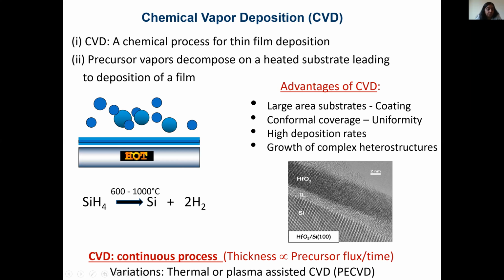Sometimes you do thermal CVD, so you go to high temperatures. In case you want to grow films at lower temperatures, then you can introduce another parameter, that's plasma, that can bring down the temperature of deposition drastically. So it's called plasma enhanced CVD.